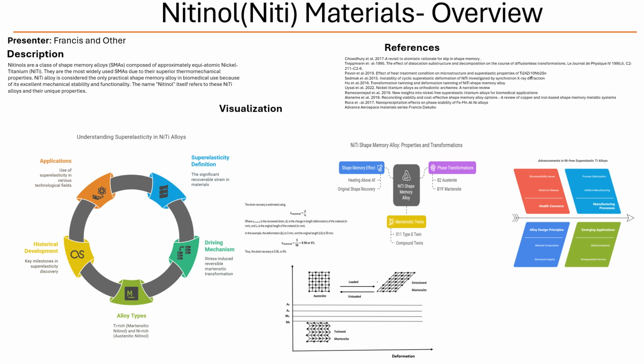That makes sense. You wouldn't want an arch wire to suddenly become stiffer or weaker just because someone took a sip of hot coffee. But I've also heard some concerns about the nickel content in these alloys. Is that something to worry about when they're being used in the body? That's a very valid concern. While NiTi is generally considered biocompatible, there are worries about it corroding in the mouth. The environment in there is pretty harsh, with changing pH levels, temperature fluctuations, bacteria, and all that mechanical stress from chewing and talking. And when NiTi corrodes, it can release nickel ions, which can cause allergic reactions in some people. So even though it's widely used, there's a potential risk of allergic reactions.